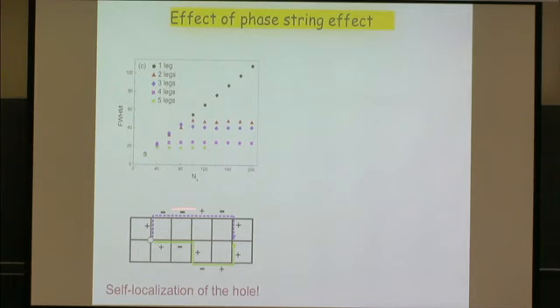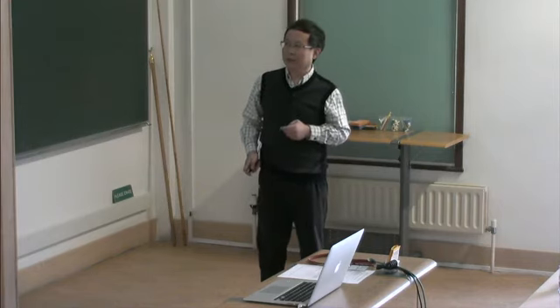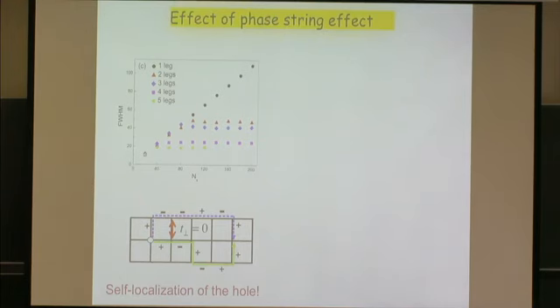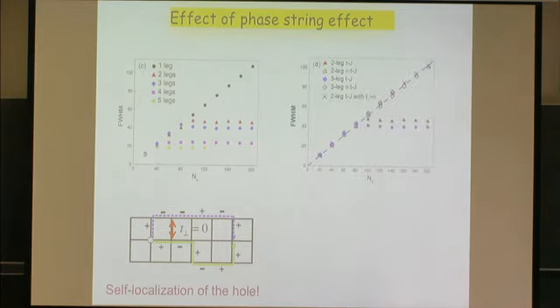That's because different paths will have strong destructive quantum interference, such that eventually the hole will be localized in space. This is not Anderson localization. This is a translationally invariant system. This is really beautifully strong quantum interference of this sign structure. If you turn off the interlayer, interchain hopping, then you don't have this interference, and you find that it actually goes back for the 2-leg case and the 3-leg case.